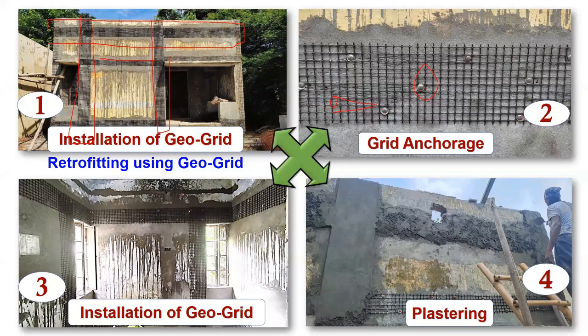And you can see this is the internal side and the external side. And then the mortar is also normal cement mortar, but the ratio is not 1:4 or 1:5; it is 1:2, or 1:3, I don't remember exactly, something like that, with latex modification, so that bonding issues and further cracks should not happen, a waterproofing kind of effect. So we made it very perfectly using latex modified materials.